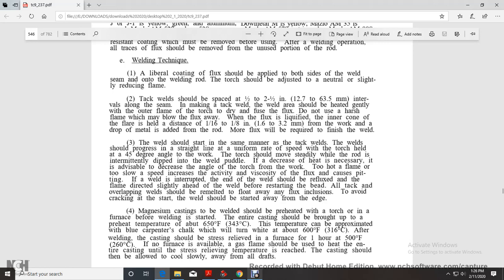The weld should progress in a straight line at a uniform rate of speed, with the torch held at a 45-degree angle to the work. The torch should be moved steadily while the rod is intermittently dipped in the weld pool. Vary the heat as necessary by varying the angle of the torch to the work. Too hot a flame and too slow a speed will increase the activity and reduce the viscosity of the flux, causing pitting of the weld. If the weld is interrupted, the end of the weld should be refluxed and the flame directed slightly ahead of the weld before restarting the bead.